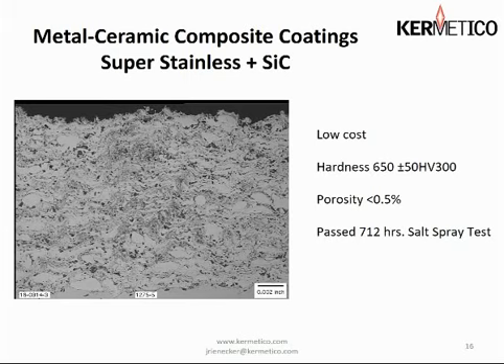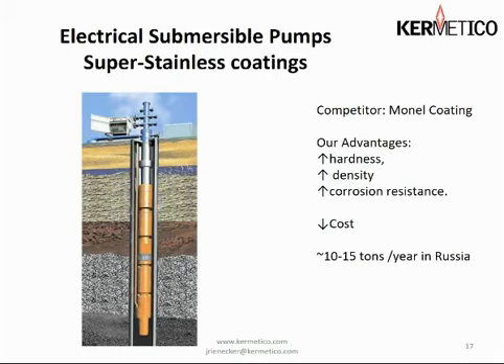Pretty impressive results. There's an application that was done by our customer in the Russian Federation. They're having a lot of problems with their electrical submersible pumps, ESPs. The outside of the housings are being eaten alive by the rough layers of shale and whatnot they're going through. So we were able to apply, and they did, a coating that we worked out together, a combination of 6AB directly onto the housing, followed by Super Stainless 350. A combination of those two coatings made for a corrosion-resistant and wear-resistant coating that significantly improved the performance of the housings. They're spraying somewhere between 10 and 15 tons a year at our customer in Russia of those two materials on these ESPs. We're talking about kilometers worth of ESP housings here.